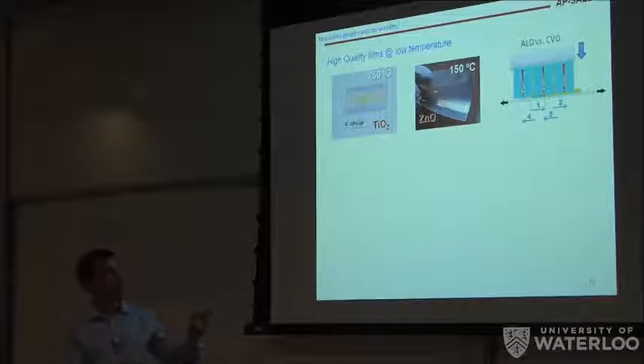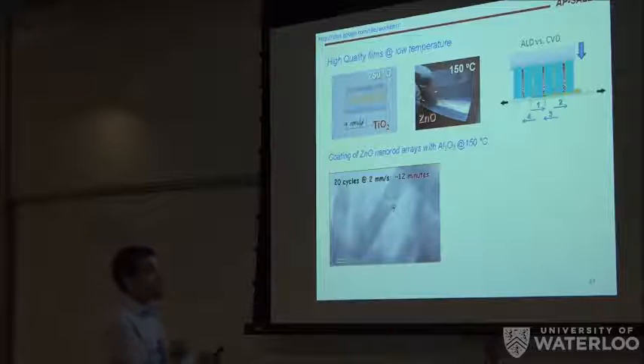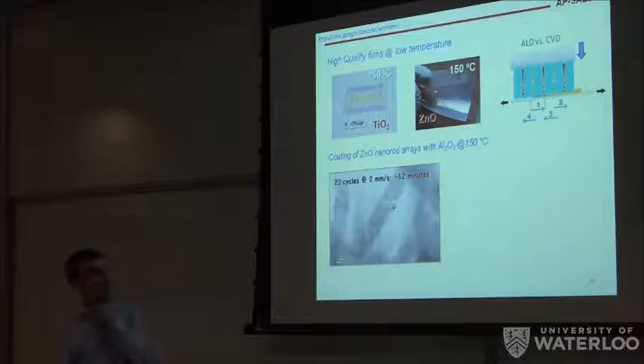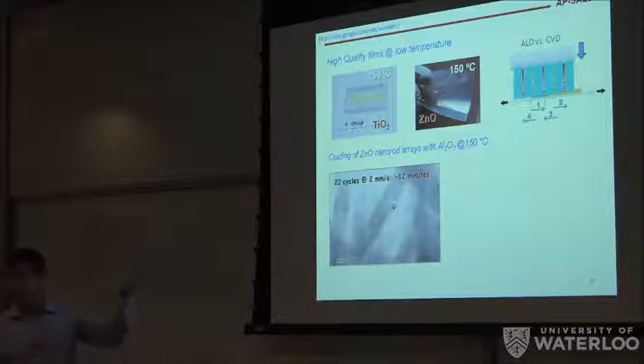And that's an advantage because for this kind of substrates where you don't have any complicated feature, high aspect ratio, you don't care whether you're actually doing CVD or ALD as long as your film is uniform, dense, crack-free, no pinholes, and you manage to go much faster because you go from ALD to CVD, so you are speeding the reaction a lot. And we wanted to try these two approximations on nanostructures to see also how conformal the deposition would be, because ALD is supposed to be conformal.